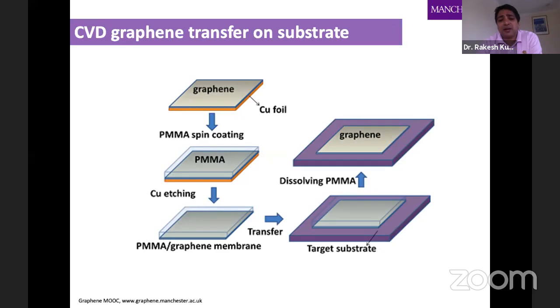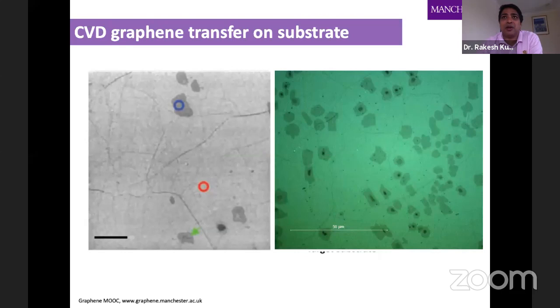So there are so many challenges even during the transfer, because most of the transfers are wet transfers, and during the transfer you trap a lot of impurities and even water molecules that affect the properties of graphene when it's on a substrate, because the interaction between the substrate and graphene film, it's just a single layer with pi electrons. So any charge impurities will affect its electrical and chemical properties. So we're still working on how to improve the graphene transfer method. There are dry transfer methods, but it's still challenging how to do a large scale dry transfer, like 6-inch or